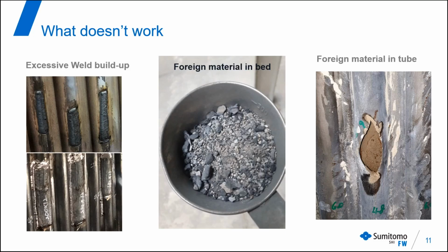On the left, we can see weld buildups on the tubes where there has been earlier corrosion or erosion. If those weld buildups are left like that, there will be a swirl of bed material on the top of the weld buildup, and the tube will start to erode on top of that really fast.